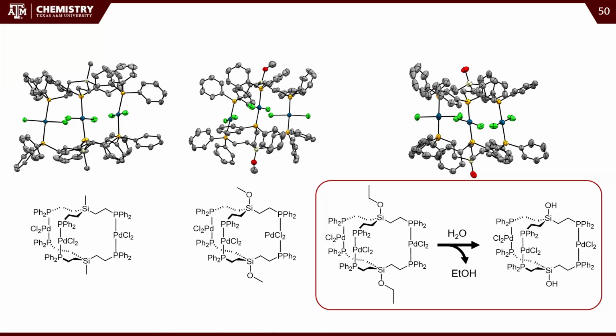So I tried for, I don't know, 5 or 6 months with every solvent under the sun, and vapor diffusion and solvent layering, and we never got there. Instead, it would just make amorphous blobs. And then I would set that on the counter and hope. And a month later, I would get crystals. What happens is just water gets in and cleaves, and you make this silanol. And the silanol crystallizes, no problem, easy peasy.